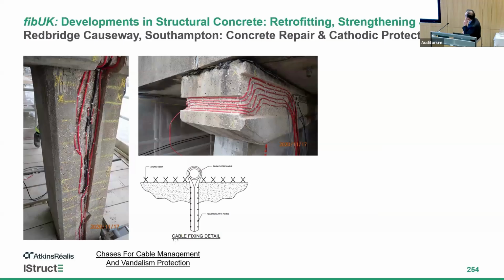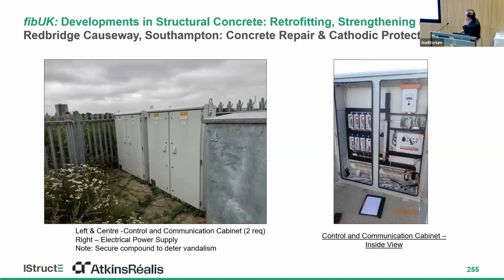Again, the challenge about cabling: you could see the size of the cable chases that we had to cut. And in order to avoid delamination and debondment of the repair mortar within the chases, spacing between the cables was very important. So allowing for spacing and the number of cables to be chased is always a challenge, especially if you have low cover areas at the reinforcement, which we had to overcome.